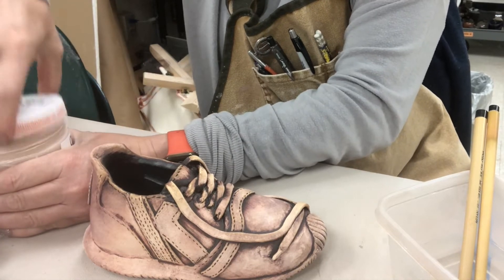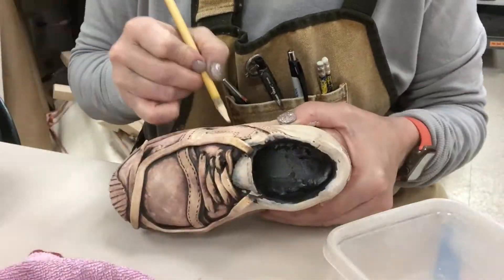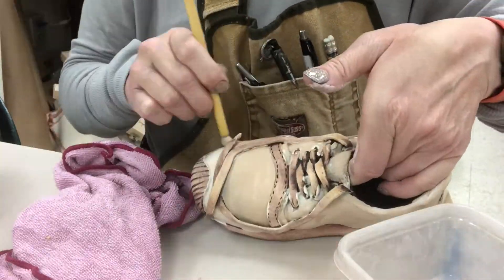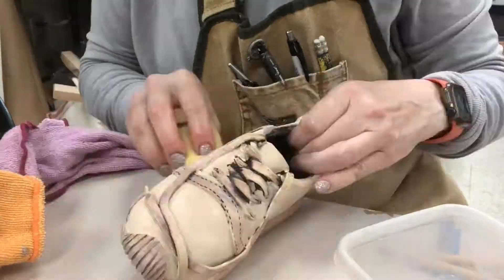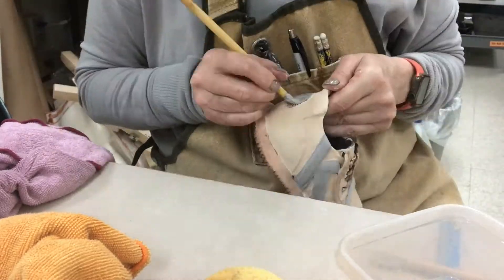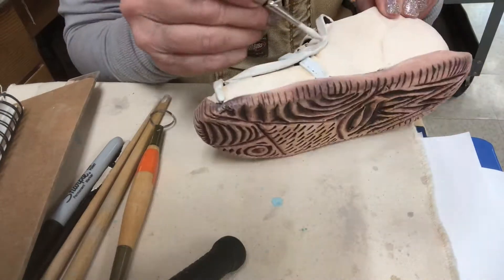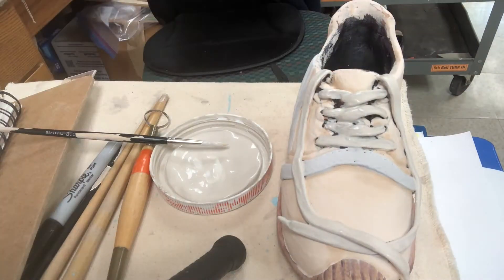My class is using the Cone 6 Coyote Glazes. These are great for brushing and dipping, but we're going to be brushing or perhaps using a bulb syringe for application. Brushes get three coats; with a bulb syringe you use one — we learned all about that on the little box sampler. As I apply the glaze, I want to be mindful of the lace details. If I get orange on the laces, I want to wipe that off before applying the lace glaze — you don't want to sloppily apply one over another as it will smear during firing.